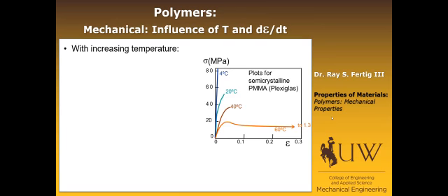Well, what I'm showing you here is a plot of a stress strain curve for PMMA, that's polymethyl methacrylate, which is just, you know, Plexiglas. And this blue curve shows that brittle type behavior we were talking about, and that's occurring at 4 degrees C. As we heat the material up, we start bending around till at 60 degrees C, we're now observing the elastoplastic behavior. So a single material, depending on the temperature, can actually take on multiple mechanical characteristics from the classes that we talked about previously.